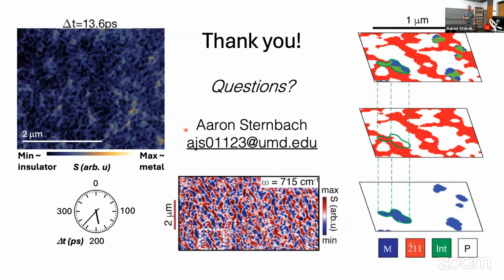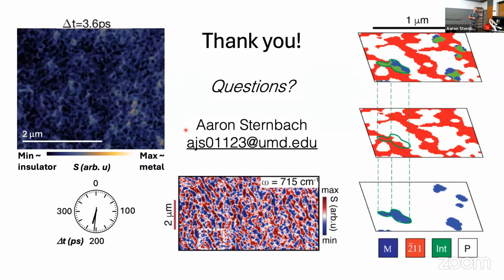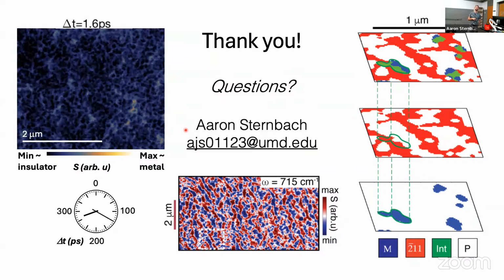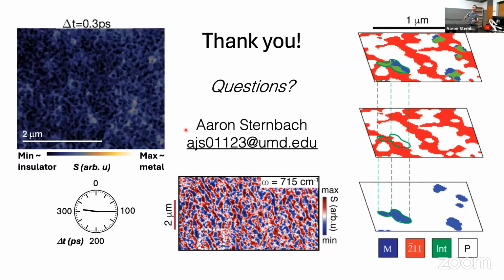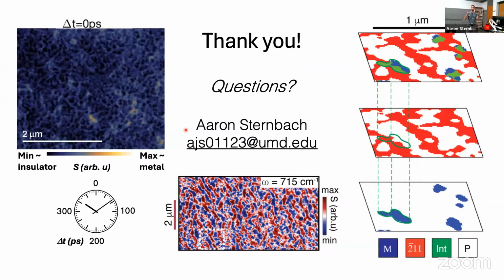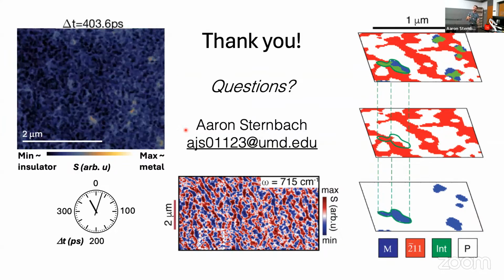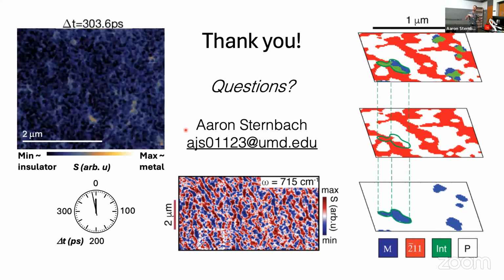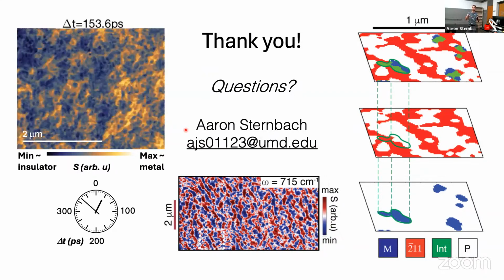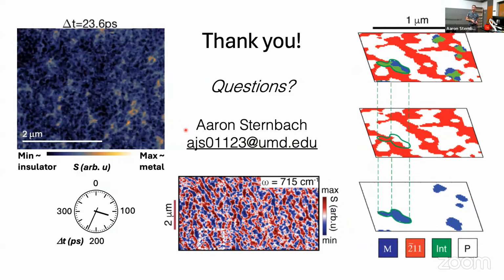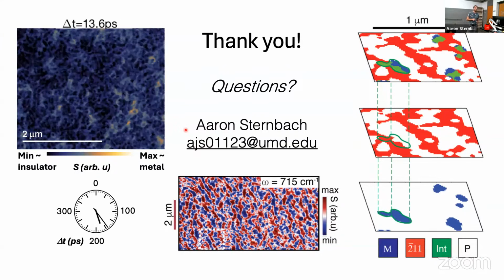From the point of view of the setup of the near field microscopy, how do you decide the location of your detector? Because the scattering is taking place in all directions, right? So when you're talking about outside of the microscope, way away from the tip. The decision of the optics really goes back to Fritz Keilmann's papers, and I'd encourage you to read those. They're fantastic papers, analyzing the dipolar radiation pattern that you get from this tip and why you should put your mirror here versus there. But yes, it comes out as radiation at all angles, and you collect some of that with a parabolic mirror and send it to a detector. We perhaps lose a significant fraction of what is scattered because we're only collecting a certain angular range, but the signal to noise is still decent enough.